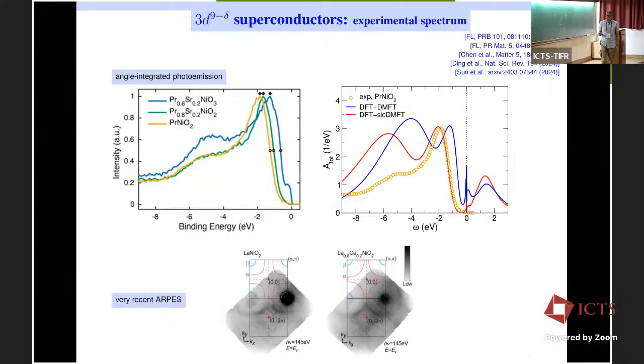I also have to say that very recently there have been RIXS measurements that see some dispersion of X minus Y square in the second Brillouin zone, not in the first, but it's very weak. In our calculation, it's like a zero, so X minus Y square is fully Mott insulated. Of course, measuring a zero is difficult. We will likely measure maybe something, and that is seen here.